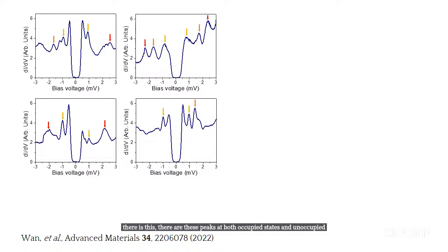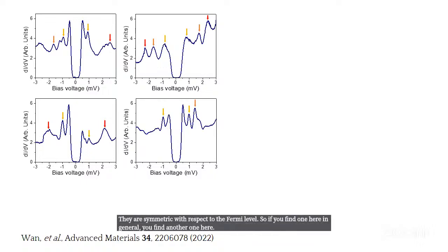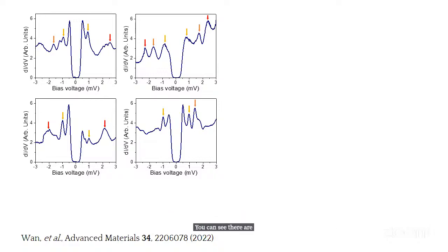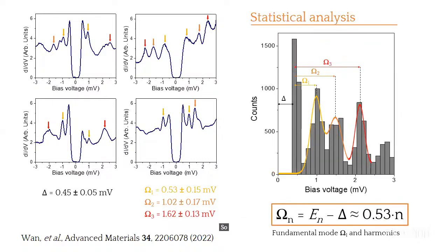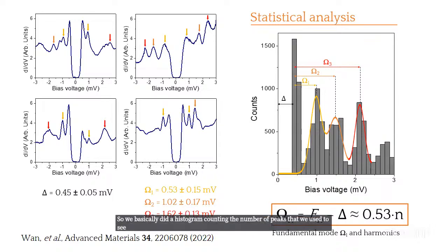In general, they are symmetric with respect to the Fermi level. So if you find one here, in general, you find another one here. You can see there are series of these peaks. So we put this into numbers. We basically did a histogram counting the number of peaks that we used to see in statistically different dI/dV curves. And here is the result, okay?